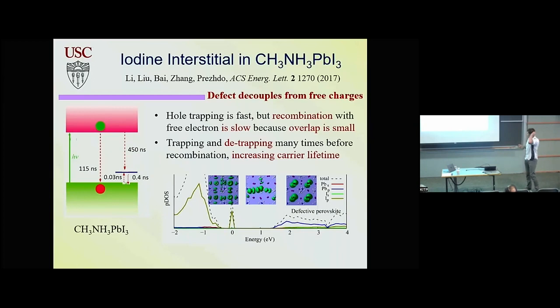So for interstitial, you have a trap state, but when the hole is trapped in this trap state, it does not recombine with the electron, because one reason is that this material has a very sparse inorganic lattice, and the trapped charge does not couple with the other charge. So the overlap of the wave functions is very small because the lattice is very wide and you have lots of space in the middle. So the trap states that are created are decoupled from the band states.